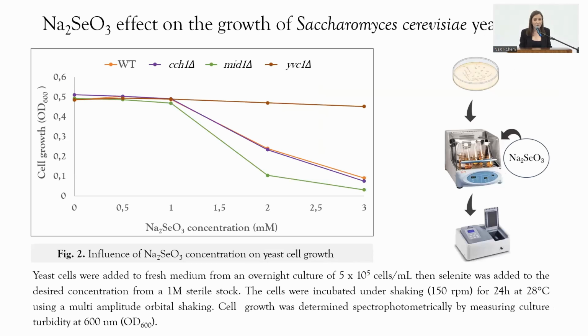The mutant strains were also grown in liquid YPD media in the presence of sodium selenite over a period of 24 hours. After these 24 hours of incubation, the optic densities of the cultures were measured. The values were represented graphically in relation to sodium selenite concentration. These results confirm the previous ones. The growth of the MID1 knockout strain drastically decreased at high concentrations of sodium selenite, exceeding 1 millimolar to be more precise. And the YVC1 knockout strain was indeed the most resistant strain.